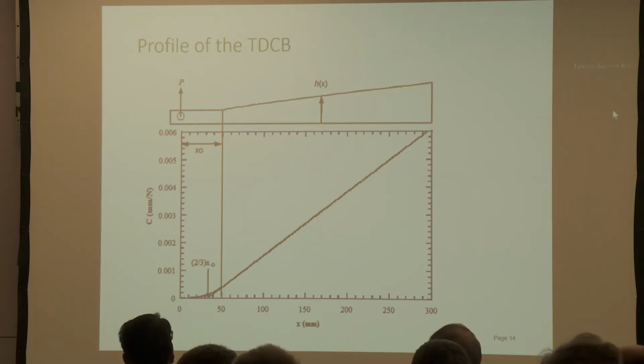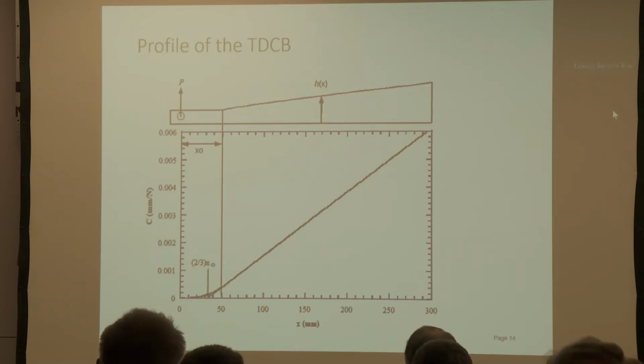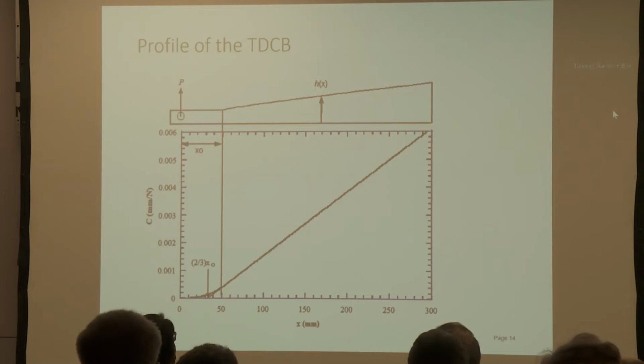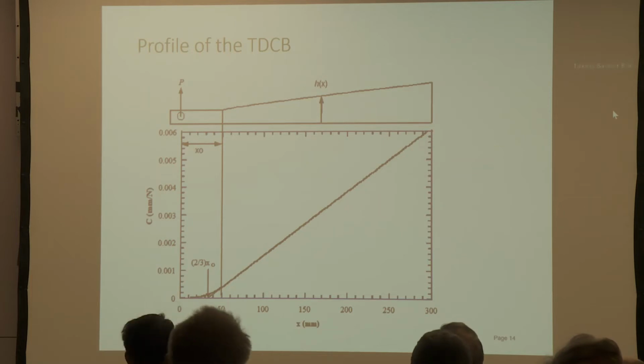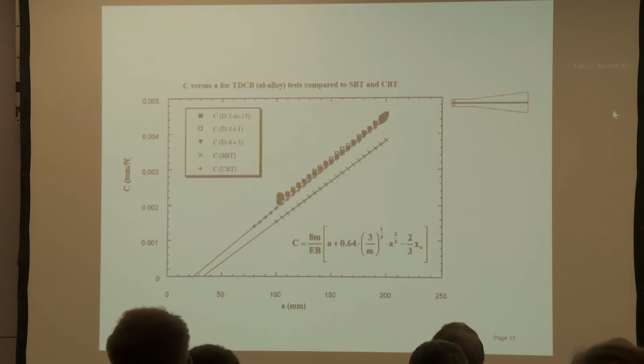And you can see that if one extrapolates the linear changing compliance to zero compliance, you actually get an intercept at some portion of the untapered region, x0. It turns out to be 2/3 of the length. But that's, if you like, a compliance error that you run into if you assume the beam profiles down to zero crack length. And the second thing that needed to be looked at was the root rotation. So the original shear-corrected beam theory didn't take the root rotation term into account, which has important consequences.